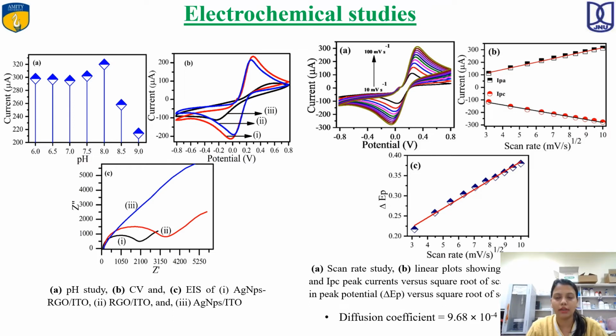Then the electrode study of silver nanoparticle, reduced graphene oxide, as well as the nanocomposite was taken and fabricated using the indium tin oxide, that is the ITO electrode, and you can see the best results are obtained in the composite, that is due to the synergetic effect of silver nanoparticle as well as the RGO. And in case of EIS, you can see there is a total reverse trend of what we get in CV, that is, in CV it shows the highest current, while in EIS, that is electrochemical impedance spectroscopy, it shows a resistance. Then there is a scan rate study which shows that it is a diffusion controlled process, and also a diffusion coefficient of 9.68 × 10⁻⁴ was achieved.